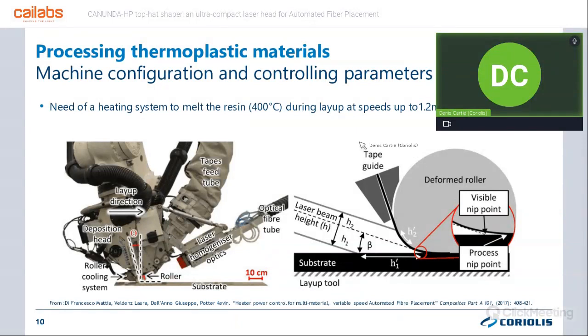On the picture on the right, you can see a bit better the tape which is being fed through a guide, and then the roller applying pressure on the surface. And in order to control the process, we heat the material with a high power laser beam. As you can see in the picture, we need to reach a melting temperature or above melting temperature of the composite, which is on the order of 400 degrees C. And in the case of fast layup, this 400 degrees C needs to be achieved while the head moves at speeds up to 1.2 meters per second.